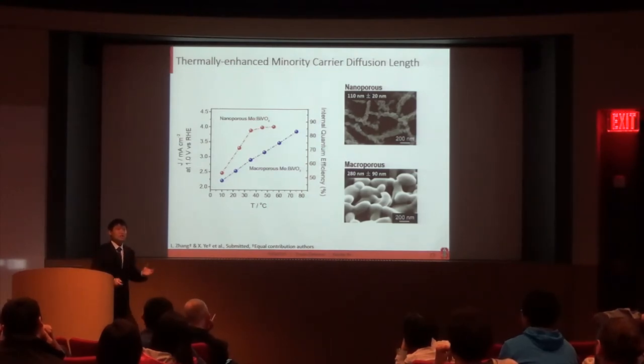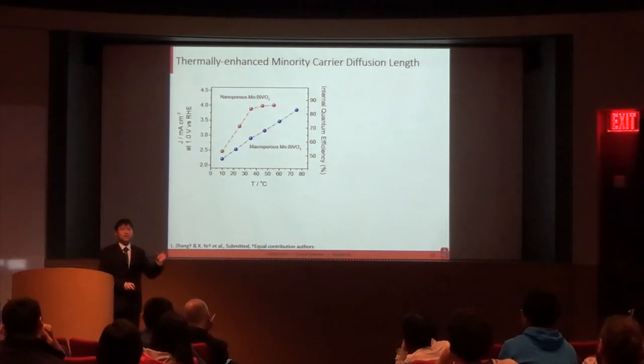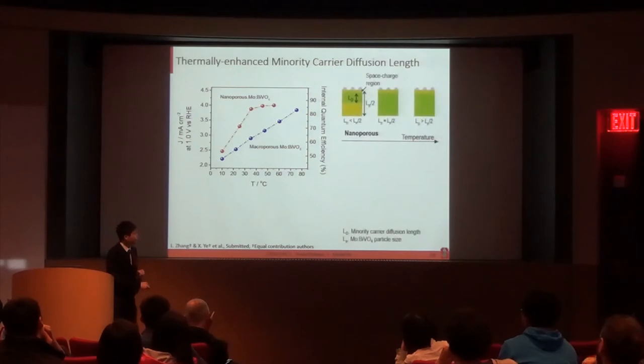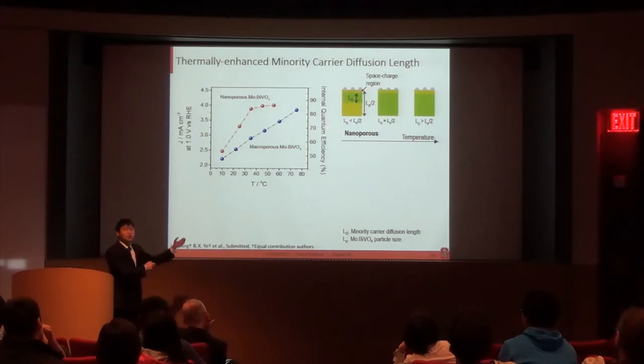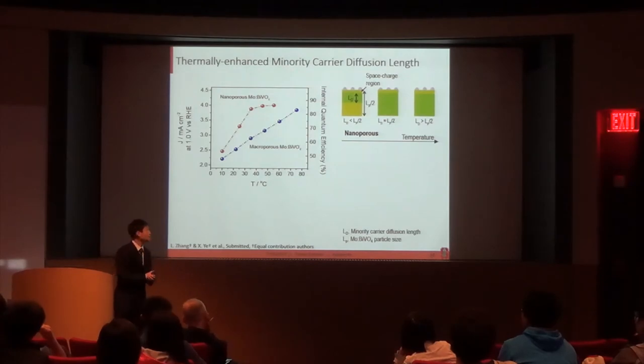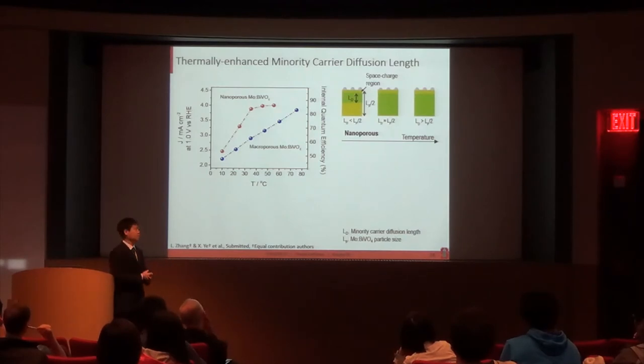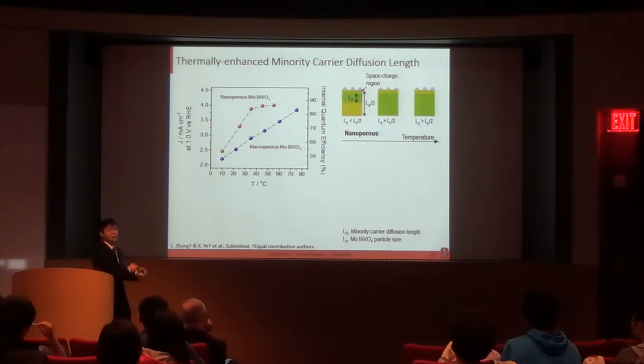So we can rationalize this different temperature dependence with the same schematic picture that we used for minority carrier diffusion. In nanoporous BVO, we know that at lower temperatures, the minority carrier diffusion length is smaller than the particle size. So that's why it determines the photocurrent yield. As the temperature increases, the diffusion length increases, so the photocurrent increases. But there's a critical temperature at which the minority carrier diffusion length becomes comparable with the particle size, so that it no longer determines the photocurrent. As you further increase the temperature, you will see this plateau in the photocurrent.